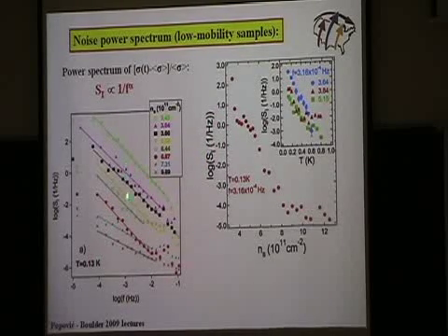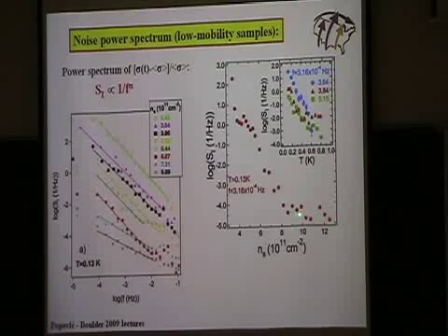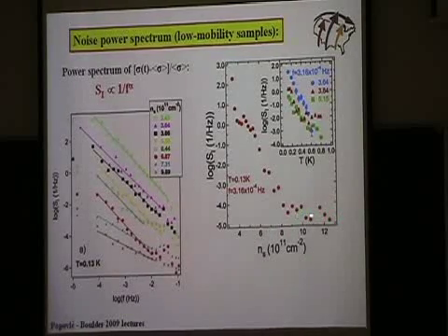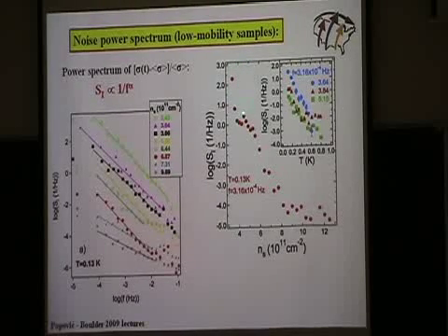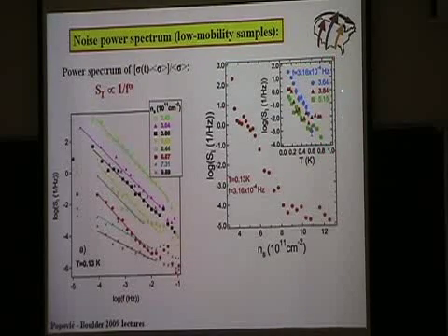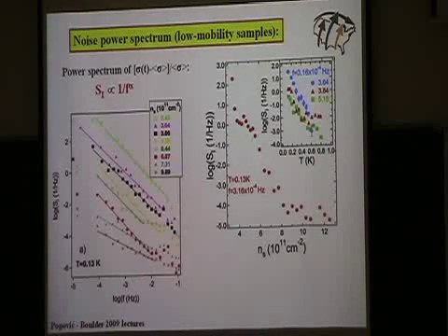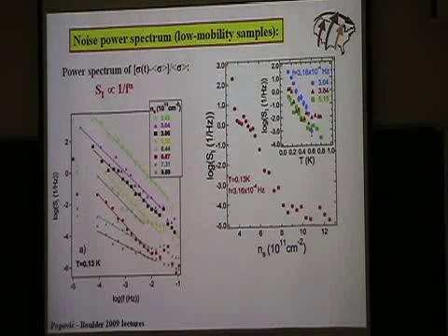So for a fixed low frequency, as a function of density, just as what I showed you before for the variance, there is no dependence at high densities. And then below Ng, which is here, we see a huge exponential increase of the noise at low densities. So in the glassy regime, the noise goes up rapidly. And the inset shows that for a fixed density, say one of these, as we lower the temperature, it also goes up exponentially. And this also helps to rule out some simple mechanisms for the noise.